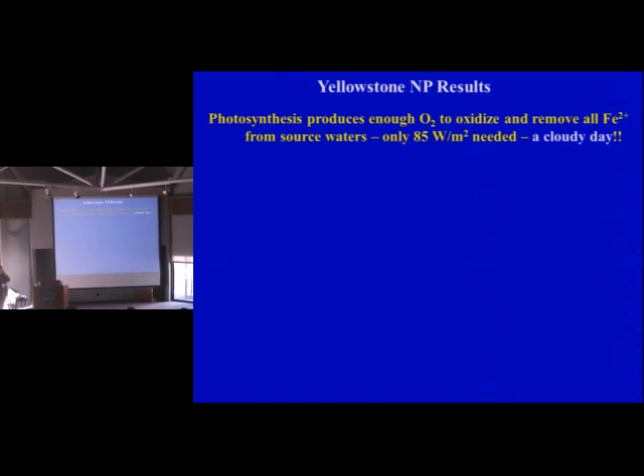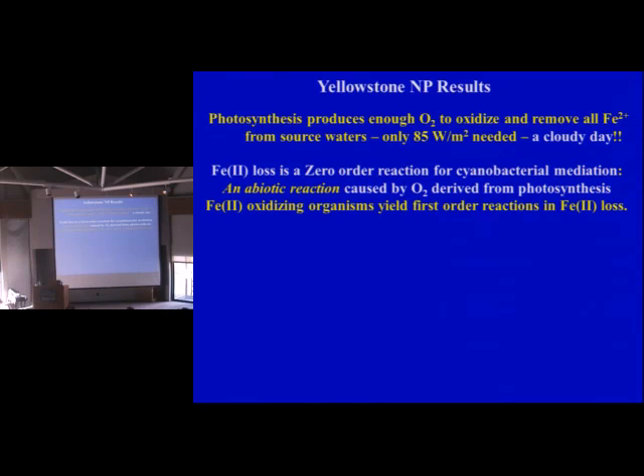For photosynthesis, we're producing oxygen. It's taking out all the iron 2, but not the manganese. And even a cloudy day is enough to take out all the iron 2 in these waters at about 150 micromolar. That's the highest we actually had. The iron 2 loss is zeroth order. And this indicates that we have an abiotic reaction caused by the oxygen derived from photosynthesis. And the iron-oxidizing organisms would yield first order, as I'm going to show you shortly. Also, they work both in the dark and the light. All right? Manganese 2 is not oxidized and removed at these pHs.